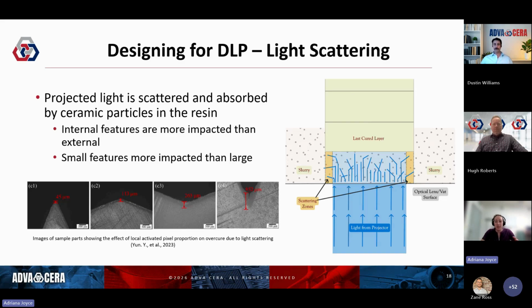This effect is material, so the slurry that we're working with, intensity, amount of light coming up, and feature dependent. Looking at these images along the bottom, you can see that for a point, narrow versus wide, and internal versus external, we get a pretty dramatically different amount of overpolymerization, or overcure, depending on the terminology you want to use. That's because depending on that cross-section, the total amount of light density around the point of that corner is different. So on the internal angles, we've got more light coming in from both sides, increasing the total amount of scatter and therefore the amount of overpolymerization.